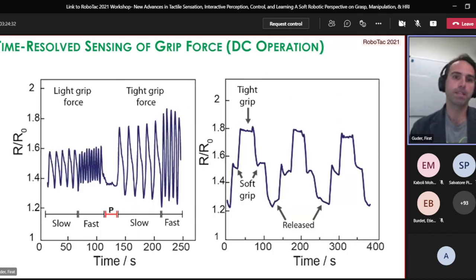We can do some time-resolved grip measurements, and by changing the grip force, we can easily see that the signal increases, and we can do faster or slower grips or squeezes, and we can resolve all of these things. Our signal is not super clean, and one of the reasons is that we operated our sensor here with a DC signal, so we are susceptible to capacitive effects and drifts, which we have fixed later on.